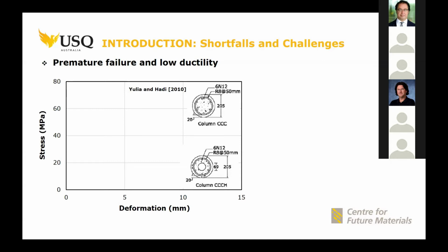As an example, one of the scholars on this topic did a study in 2010 comparing the solid with a hollow section, and you can see here it's similar in the stiffness because we are talking about stress to deformation behavior. However, the peak is different. There is a gap between solid and hollow columns at the peak. After that, the most critical part is the response after the peak, which is related to the displacement and ductility behavior. You can see here that the solid section introduced a more stable behavior than the hollow column, and the hollow column is gradually reducing the load or stress capacity.